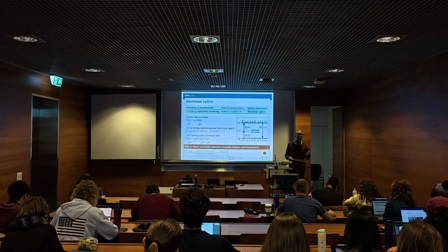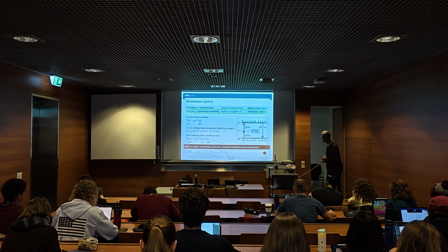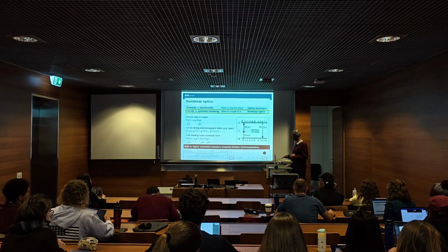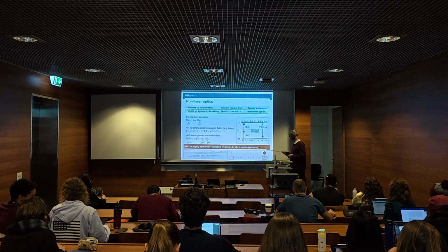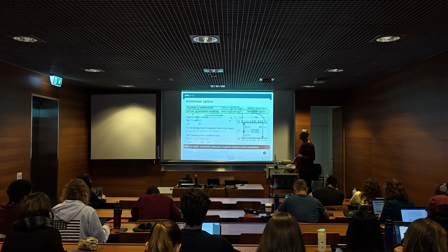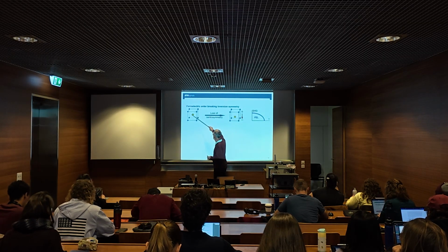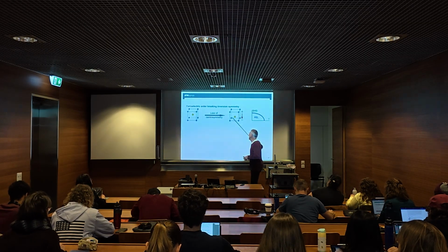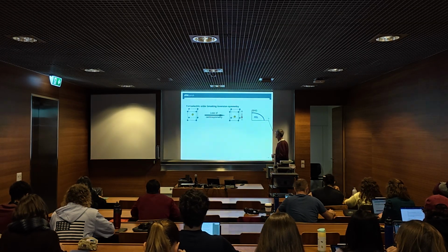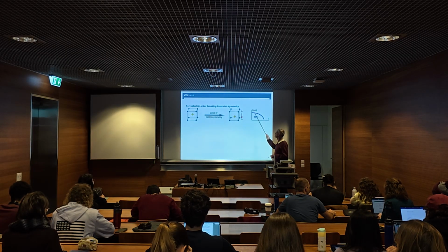You find a slide where the proof for this is written down, but for the moment I would just use that. So this is only permitted if you break central symmetry, inversion symmetry. In that sense, it's very useful for imaging the emergence of ferroelectric order, because ferroelectric order breaks inversion symmetry. You have this centrosymmetric situation, ion in the center. It moves off center, you get a polarization, and that's not centrosymmetric anymore. So right when your material becomes ferroelectric, you have the emergence of such a frequency doubled signal.